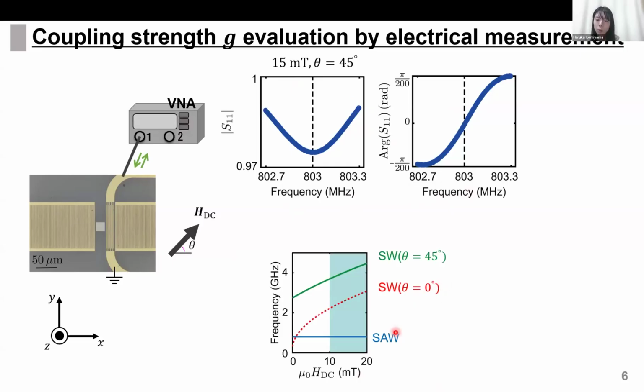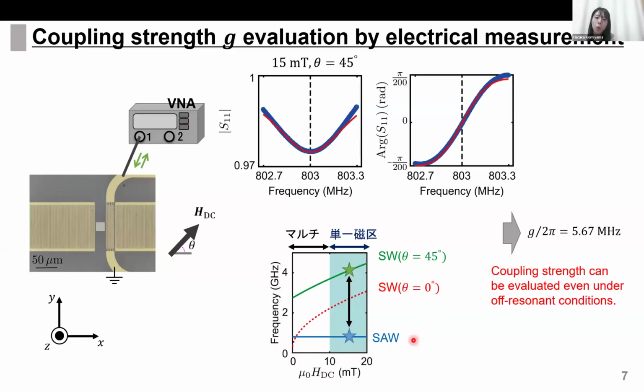Previous studies evaluating the coupling strength use magnetic field conditions in which surface acoustic wave and spin wave frequencies match. In our device, the frequency of the spin wave coincides with the frequency of the surface acoustic wave at 800 MHz only when the magnetic field is low. However, preliminary experiments confirmed multi-domain behavior in such a low magnetic field. On the other hand, under the conditions of a single magnetic domain, the frequencies of the surface acoustic wave and spin wave are separated by several gigahertz. Even under these off-resonant conditions, we evaluated the coupling strength G as 5.67 MHz by fitting with an appropriate model function.